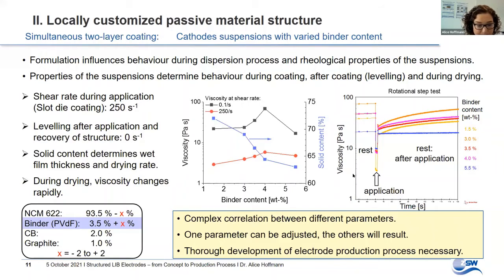Directly after the application, the leveling and reconstruction of the structure within the wet films takes place under the condition of zero shear rate. This is approximated here with these gray symbols. Because the suspensions exhibit individual shear thinning behavior, the zero shear viscosity of the tuned suspensions can differ strongly. Please note here the logarithmic scale. And also the leveling behavior, which is shown here, and the time for structure recovery vary strongly for the different slurries. What can be seen here is that we have a complex correlation between different parameters. When one parameter is adjusted for good processability, this affects other parameters that are also important for the process. Thus, for a reliable electrode configuration, the whole electrode production process has to be adjusted.